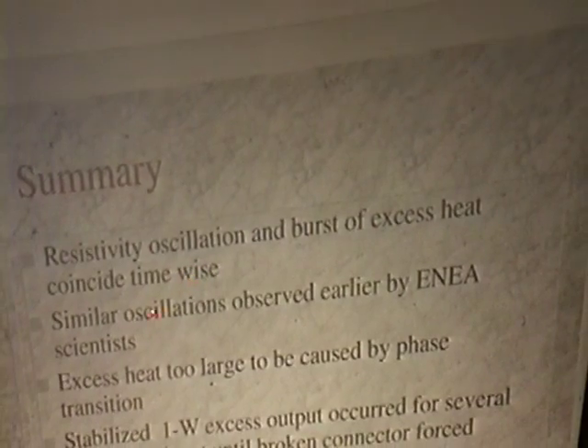So, summary of that is this resistivity oscillation and the burst coincide time-wise. This is similar to oscillations that were observed earlier at ENEA. This excess heat was too large to be attributed to a phase change or something of that nature, and the excess heat did stabilize at about 1 watt after this occurrence, and lasted for several hours, at which time a broken connection terminated the experiment.